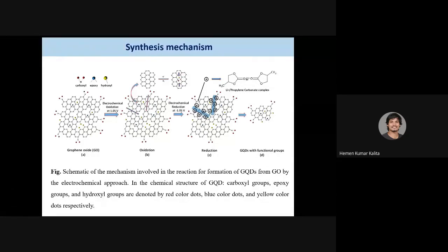In the first step, in the electrochemical approach, we apply a positive voltage across the working electrode. What happens in that step? There is a carbon-carbon bond breaking happening because of this high voltage across the electrode. The bonds in the graphene oxide start to break, and this is how it is happening. You can see this is the graphene, and then this way the bonds start to break because of this high positive potential.